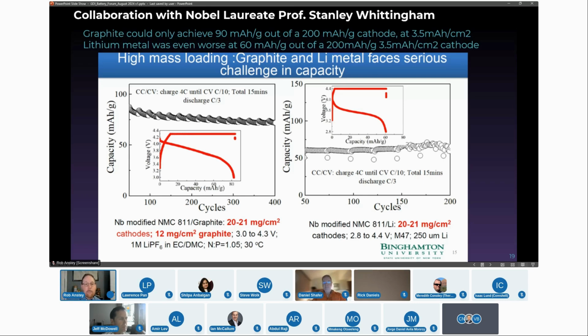Then they looked at lithium metal with the fancy new National Labs electrolyte. And that was, as you can see, atrocious. 60 out of 200 in 15 minutes. And by 150 cycles, you got a lot of dendrites and rough foil, so it's bouncing all over the place. And that was with tons of excess lithium. That was 250 microns of lithium, so you have all the lithium in the universe. And it still really, really struggled.